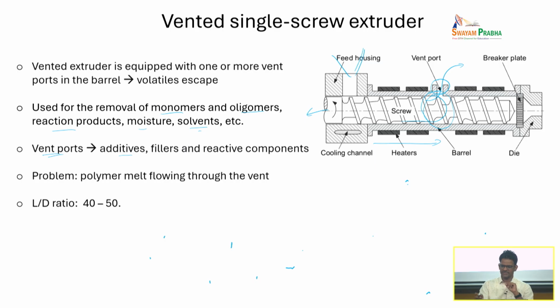And because of this provision of vent, the L/D ratio can be a little higher than the non-vented extruder. For the extruder with no vent port, we said L/D ratio can be between 20 to 30. When you have vent ports, you have between 40 to 50. Okay, and sometimes this vented single screw is more versatile. You can actually buy that. You can even close those ports. If you don't need them, you can just close those ports. You can still use it as a regular single screw extruder.